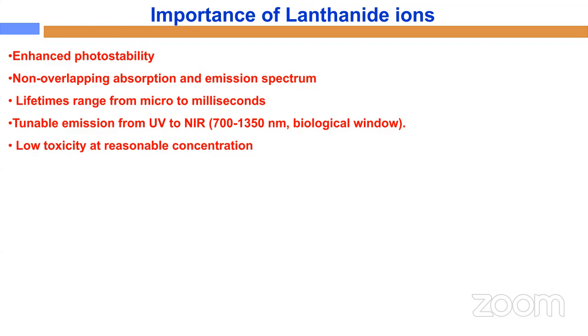What I mean by non-overlapping absorption and emission is that you can excite it in the UV region and get the emission in the near infrared region, or you excite within the visible region and get the emission in the near infrared. So you excite at 300 nanometers, and you can get emission at 600, 700, 800, like that. So there is no overlap between their absorption and emission spectra.